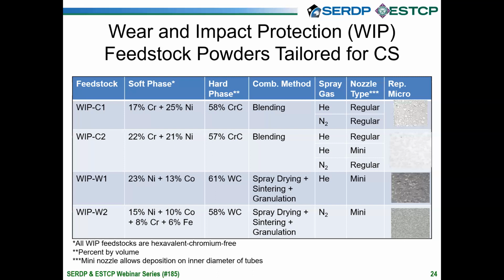We also developed cold spray processes, or what I call recipes, for each of these materials. And in some cases, we develop multiple recipes per material. So for C1 and C2, we have both helium and nitrogen spray gas recipes. And we also have miniature nozzle recipes, which allow the process to be done inside of the diameter of a tube. So altogether, 7 recipes were down selected for evaluation on the ESTCP project.